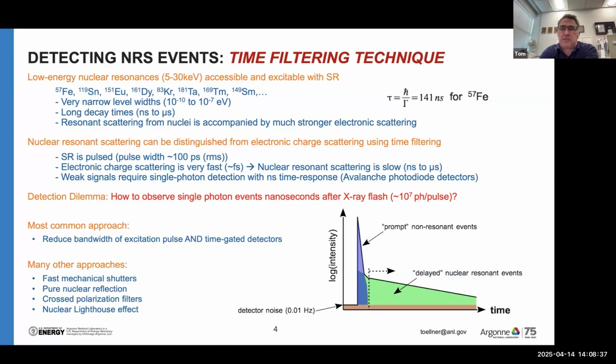So in a flash, the plot in the lower right-hand corner shows a log of the intensity. So you see a spike that corresponds to the prompt non-resonant scattering, and then the delayed. So that prompt will typically have 10 to the 7 photons in it, and then the delayed will typically have nothing, actually. Occasionally, we'll see one event after a flash, and extremely rarely you would see 2 events. You would have to go to a free electron laser in order to get any probability for 2 or 3 photon events in that time window. That's after one flash. So generally, of course, we repeat the measurement over and over again and accumulate those resonant events over time.